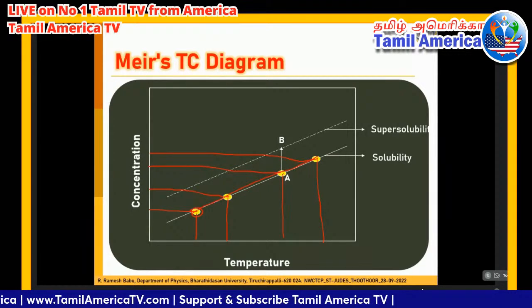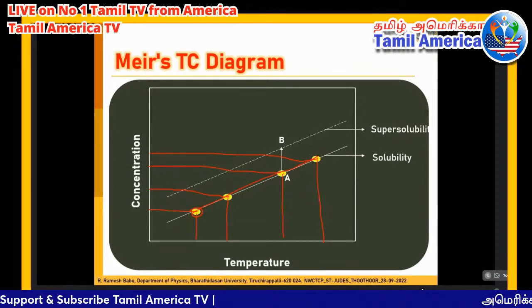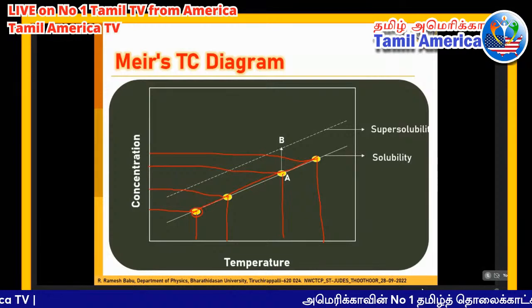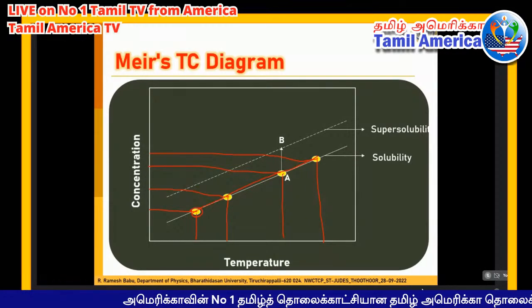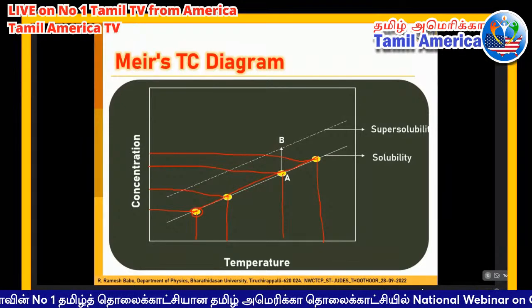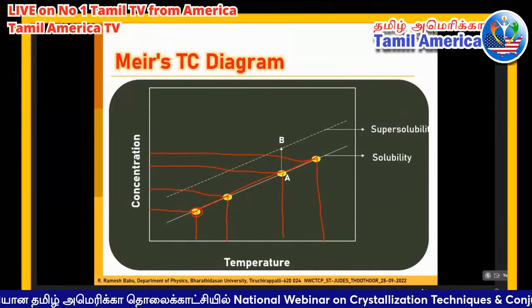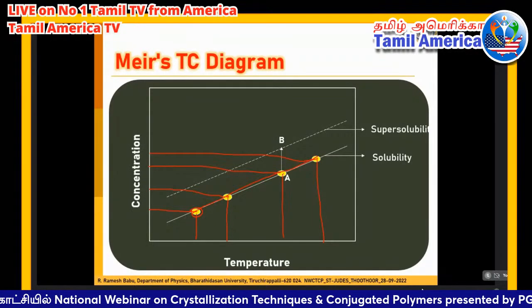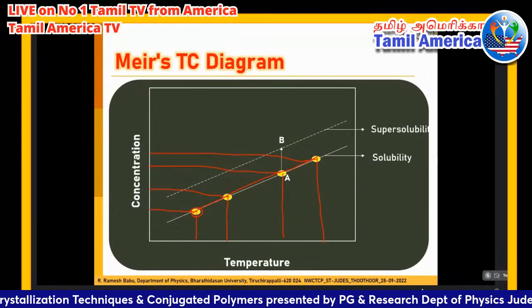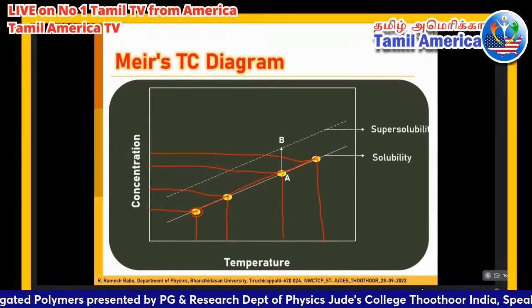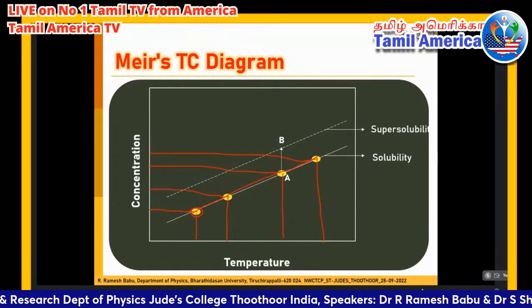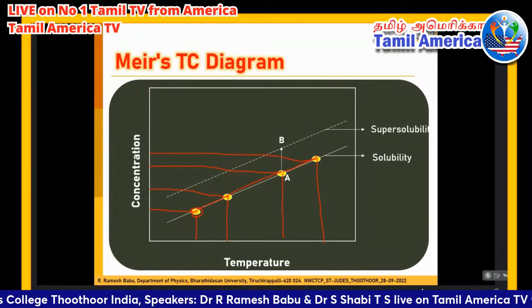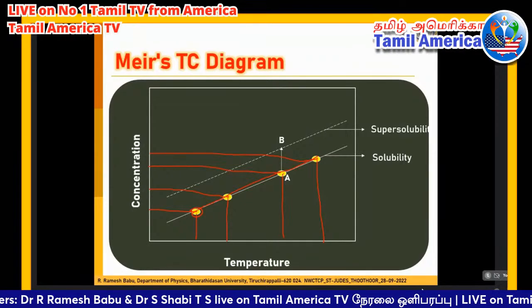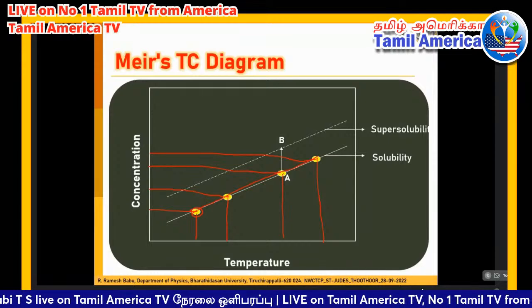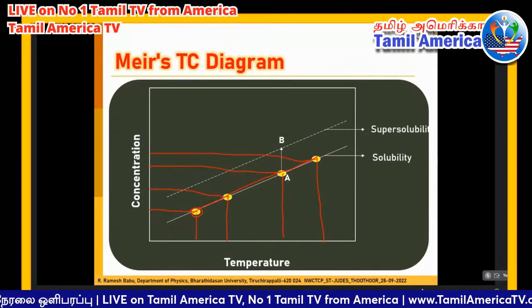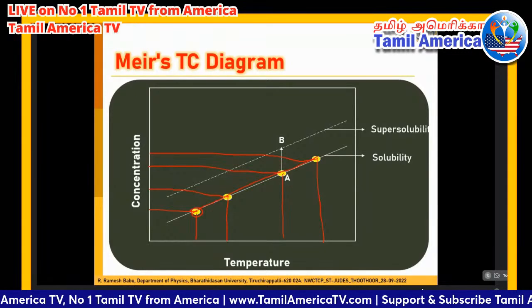Yes. We can go from solubility to super solubility, from A to B, by means of slow evaporation of solvent. The definition of solubility is equilibrium: the concentration that exists in the solubility solution is called the equilibrium concentration. Whereas in super solubility, the concentration is above equilibrium concentration, more than the equilibrium concentration. In order to prepare the solution with more than equilibrium concentration, we follow the slow evaporation technique. At a constant temperature, you just evaporate the solvent, and there we can achieve more than equilibrium concentration.